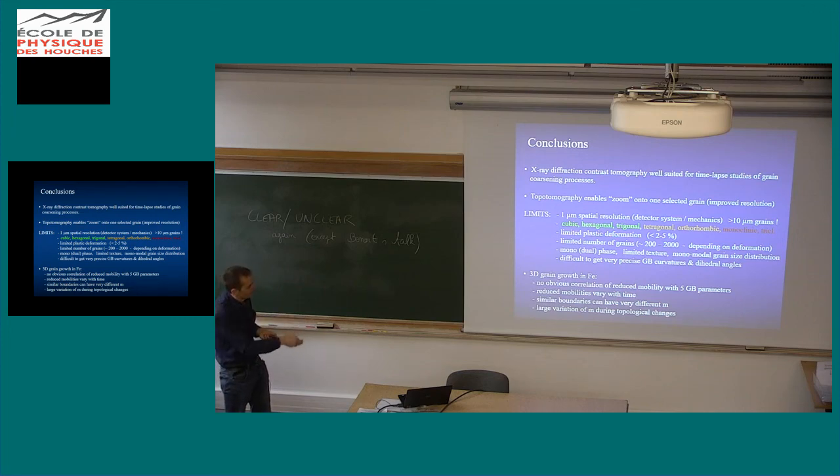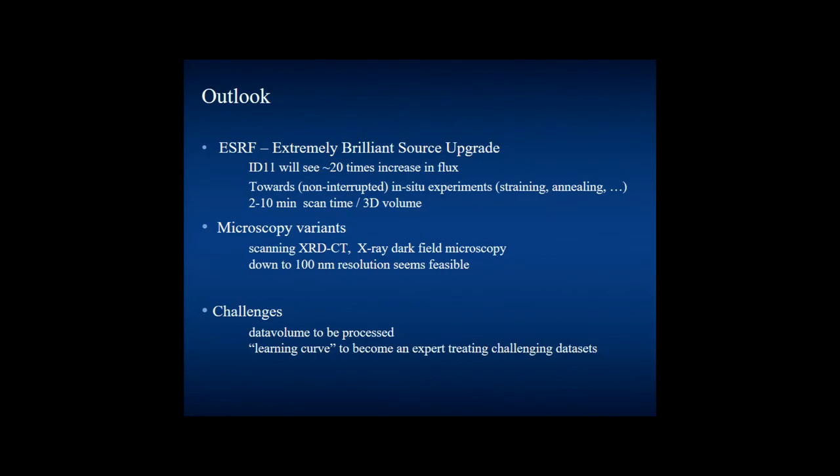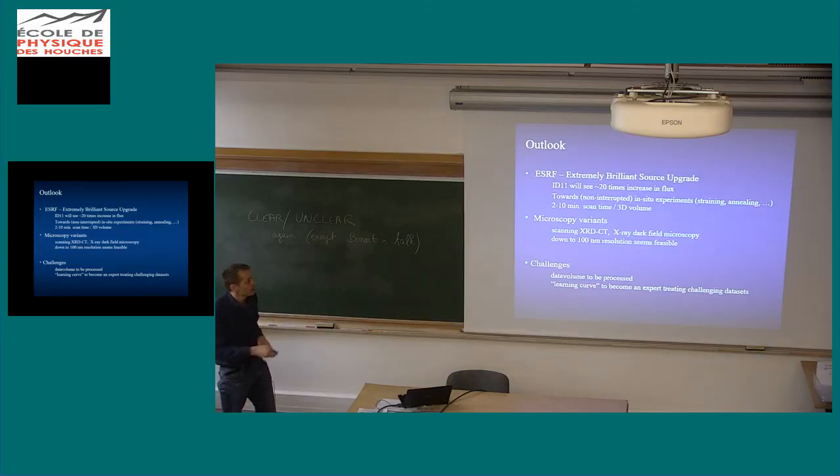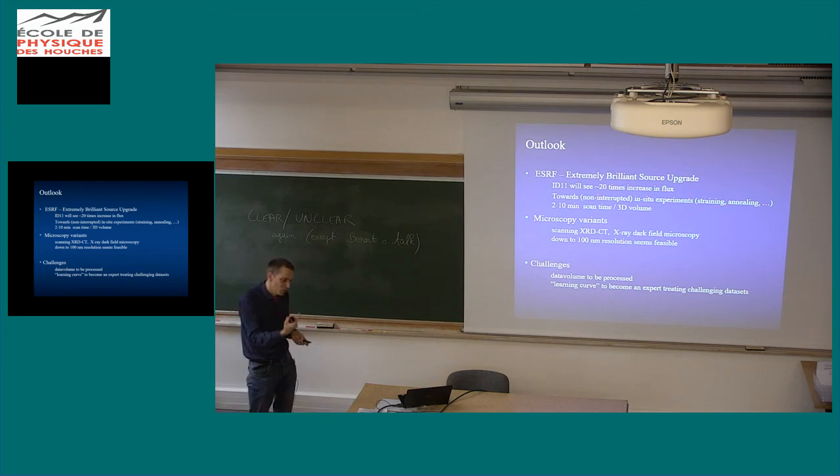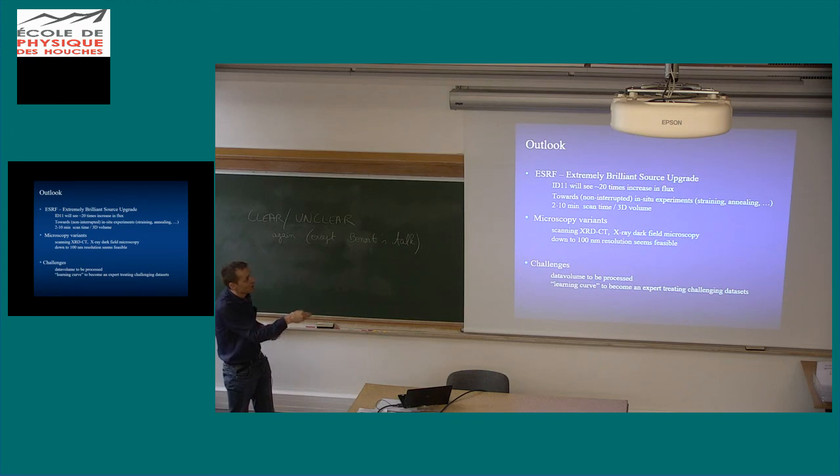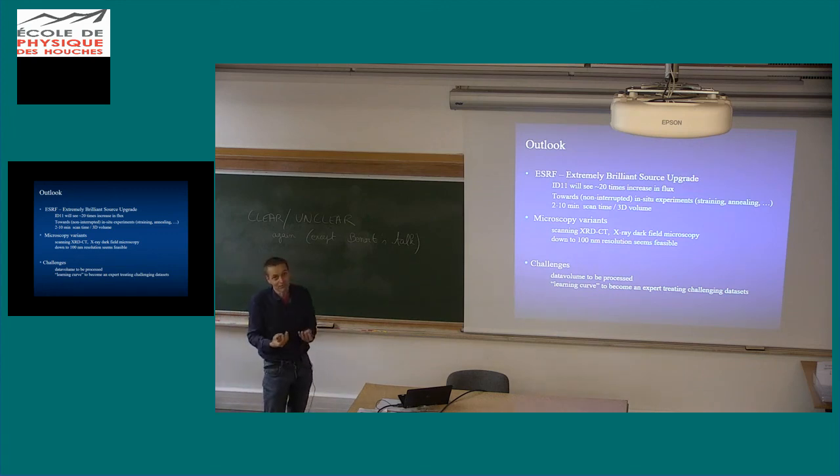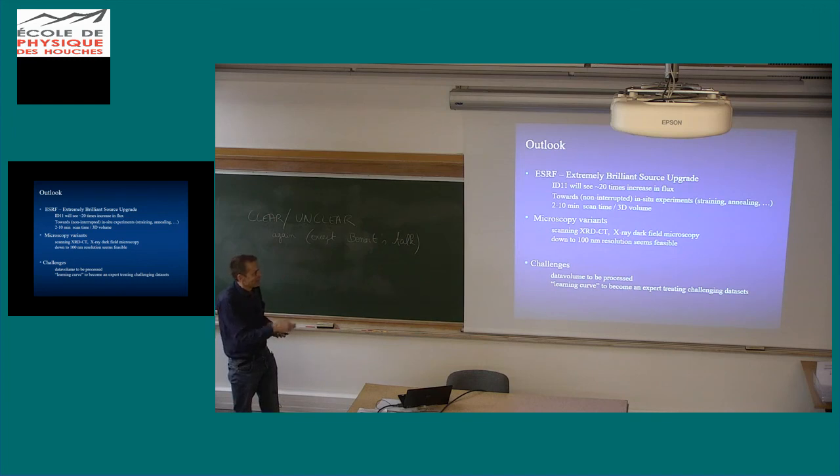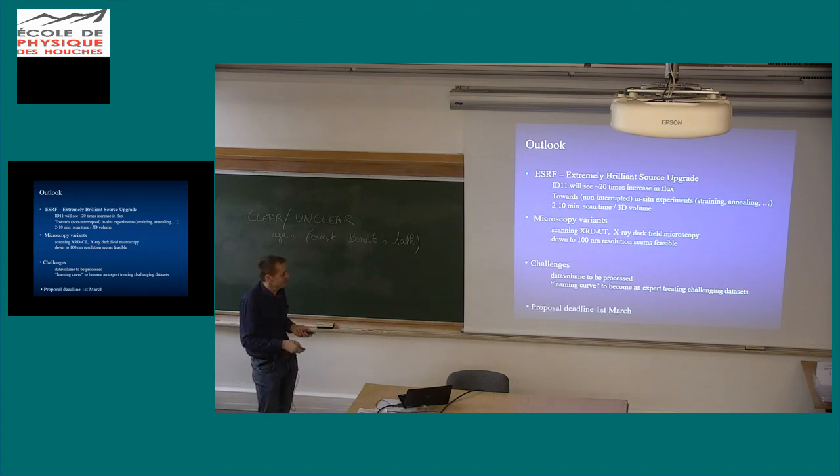And well, I think already discussed about this. Just two words about what comes next or what could be the future. With this upgrade of the synchrotron sources we see a 20 times increase in flux so that could mean that we might be able to continue without, do the observations which were all done at room temperature recycled the temperature for annealing. It might be possible to do it in situ, really staying at high temperature, provided we can construct a furnace which allows us to get very close to the sample. And scan times will come down to of order of minutes now with this improved source. You can have more resolution by doing microscopy but at the expense of temporal resolution. And there's large data volumes to be processed and there's some time to be spent to learn how to use these tools. For that reason, if you are still convinced you want to do it, then you can apply. There's a new deadline coming up, but it's challenging and time consuming to do the analysis.